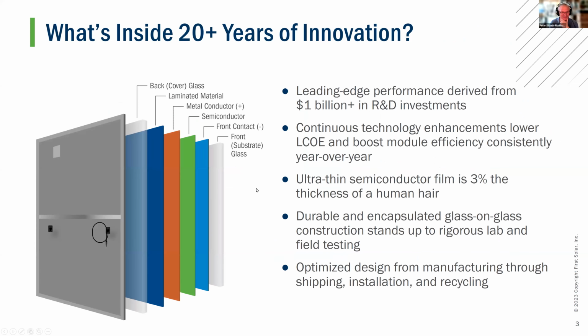So our technology is a little bit simpler than the silicon technology, which also has some significant advantages for recycling. In our case, the old modules really had no aluminum. The new ones, which have much bigger size, have aluminum backframe. And we have glass modules, so no polymer backside. You can see it consists of a front glass. Then we have a front contact, which needs to be transparent, obviously. And then we have a semiconductor, which is put on the glass in a vacuum process, and it has only a thickness of 3.5 microns. So it's really only 1% of the weight of a comparable silicon module.